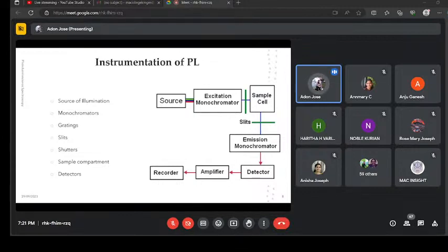Following that, we have slits, grating elements, shutters, and a sample compartment also. The source of illumination that we generally use may be a laser source or a xenon arc lamp. A quartz-based window is used to isolate the excitation monochromator from the lamp housing, because when you are using this xenon arc lamp, heat may vent out of the device. The quartz window between the excitation monochromator and the source shields against this heat, which may otherwise lead to failure of the lamp. So, to prevent that, a quartz-based window is usually present between the source and the excitation monochromator.